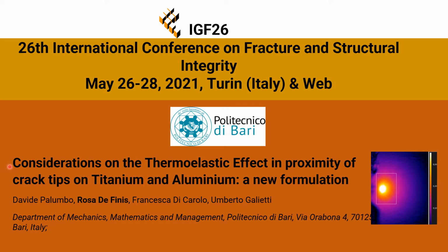Good morning, everyone. I'm Rosa de Finis from Polytechnic University of Bari, and I'm going to discuss the work "Consideration on Thermoelastic Effect in Proximity of Crack Tips on Titanium and Aluminium", a new formulation that is focused on presenting a new thermoelastic formulation that accounts for the mean stress dependence to properly investigate the stress distribution in the proximity of the crack tips of high diffusivity materials.